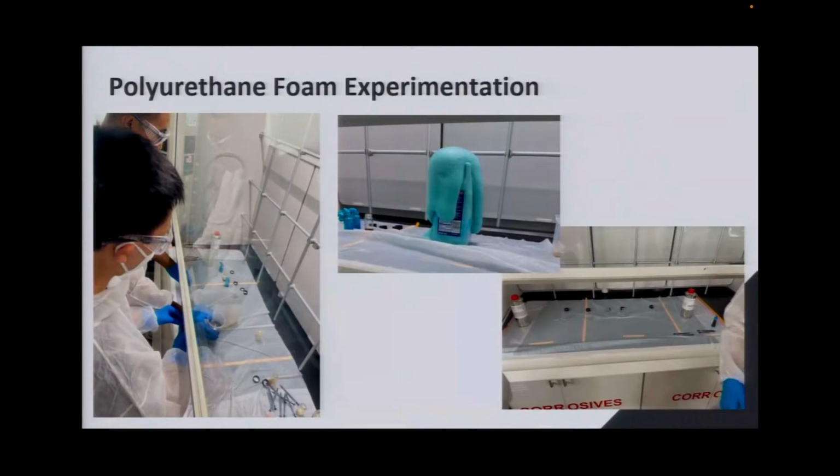Using a two-part polyurethane foam kit, we experimented with several different ratios of part A, isocyanate, to part B, polyol, catalyst, surfactant, and water to see how it would affect the polyurethane foam. We found that higher amounts of isocyanate caused the foam to be harder and more brittle.